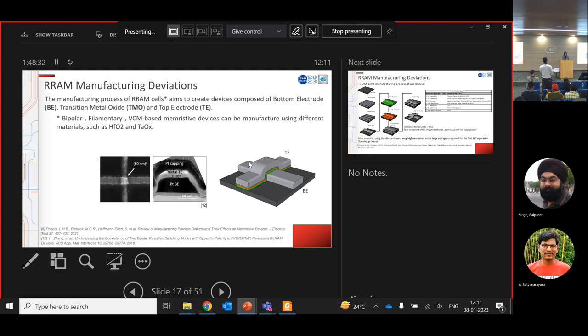Okay. So is it boiling down to the fact that the analog content that we have, we are facing a challenge in converting to digital? Is that the main challenge? I think that density is one of them, and also that you need to guarantee the integrity of those levels. From the reliability perspective, we are not talking yet about how to integrate these converters. We are just talking about the reliability of the cell itself. And with all these levels, we have a big problem with process variation, because the intervals are really close to each other. If you have variability, you cannot distinguish anymore. If you have variability, for example, in your sense amplifier as well, where you need to set a threshold, again, you have a problem.